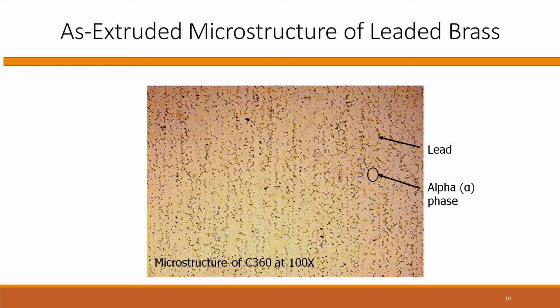What you end up with, if you've done everything right, is that yellowish alpha phase, that's the lower zinc, high copper. And then you can see now the lead particles that were in there to begin with, but were kind of obscured in the casting microstructure. The lead particles are very fine. There's about 150 million per cubic inch. That's what breaks up the chips during machining so that you get very high machining speeds.